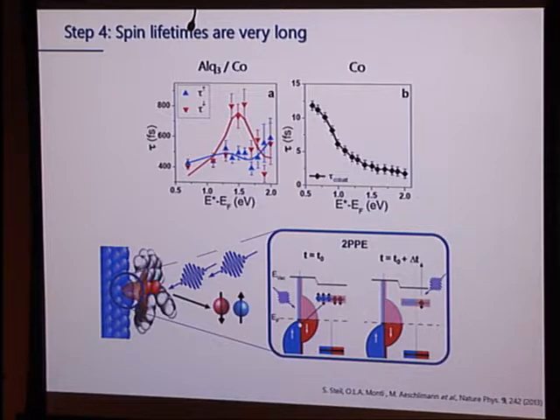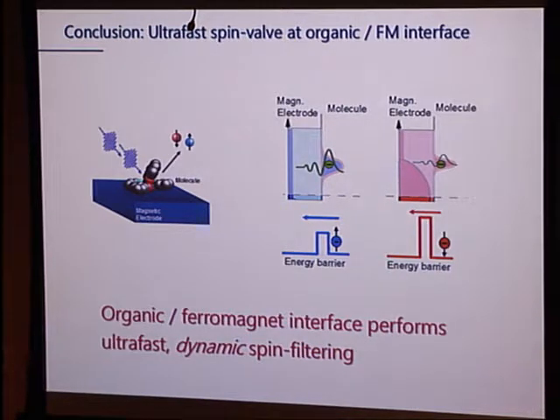So what this is telling us is that originally we populate the same amount, as far as we can tell, of spin-up and spin-down electrons, but then the spin-up ones decay relatively quickly, whilst the spin-down ones survive for a certain amount of time. So what this is saying is that we have a dynamic spin filtering process here. It happens on a short time scale, but the idea is that there is a barrier that comes about from the specific interaction of the molecule with the surface that prevents rapid back transfer in the spin-down channel, but allows it, at least somewhat, in the spin-up channel. And so at this interface, what you really generate is a fast spin-filtering process. That is just one example of what one can do at such interfaces.